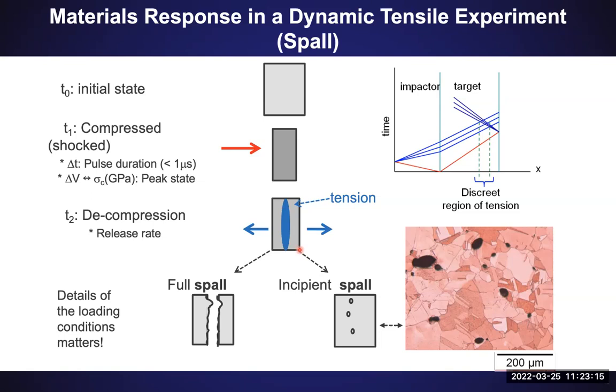The way we do this in a laboratory setting is we take a material of interest, let's say it's this light gray metal, and we can impact it with another material. So we basically have a long gun barrel that we accelerate a projectile in. That projectile impacts this material. This material gets compressed. At the time of compression, if you were to plot what's going on in this material, on the top right I have a plot that shows the position along the horizontal axis of these materials as a function of time.